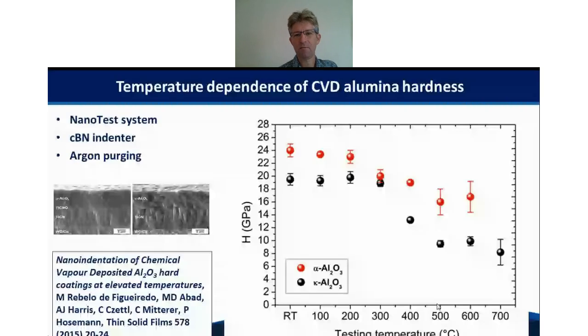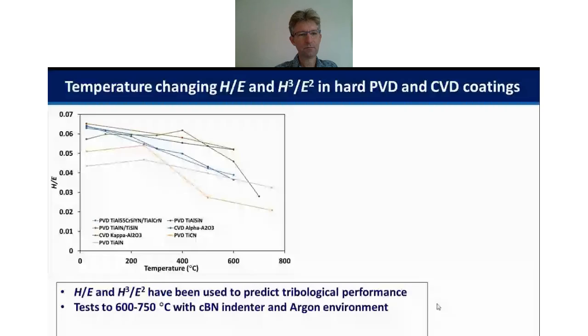Again, another example where this combination of the nanotest with cubic boron nitride indenter and argon purging has been used to look at the mechanical properties versus temperature for two different types of cutting tool material, which differ in having an alpha or a kappa alumina top layer. You can see in this example that the alpha alumina remains harder throughout the temperature range. There's a little bit of variability in some of the data, but it typically remains pretty good, and this is quite useful in explaining the tool life data.